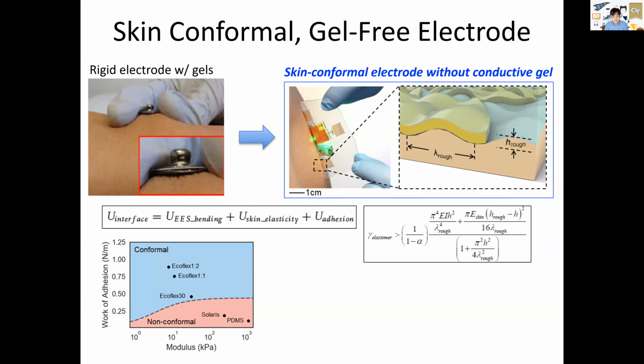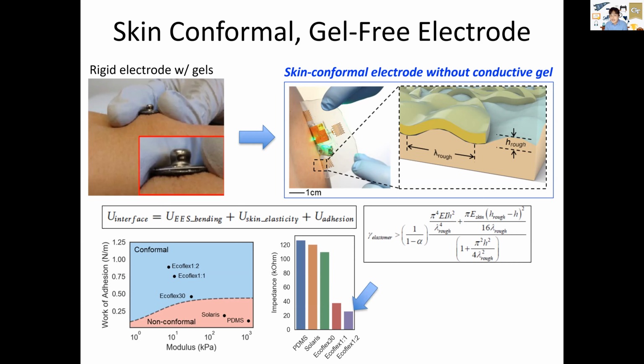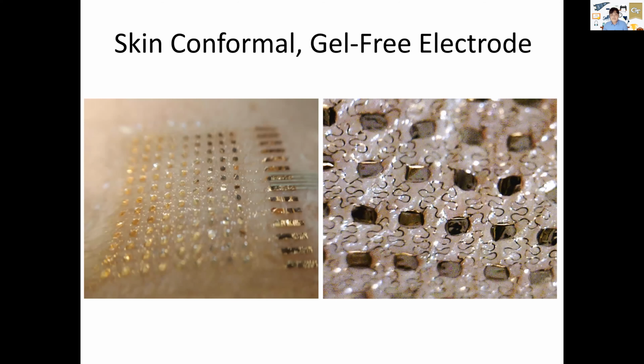So the good thing is that we can maintain the low modulus in the range of kilopascals, but at the same time, we can have good adhesion to have conformal lamination of the sensor to the skin. So once we do that, then we can lower the skin electrode impedance down to tens of kilo ohms without using any gels, which is great because now we can measure signals without any gels. So these are photos of the skin-mounted gel-free electrode. On the right-hand side, you see that the nanomembrane sensor can follow the morphology of the skin, right? Okay, so based on this arrangement, now we can measure the electrocardiogram signals.